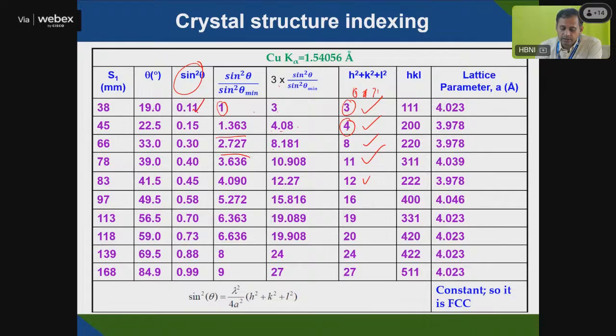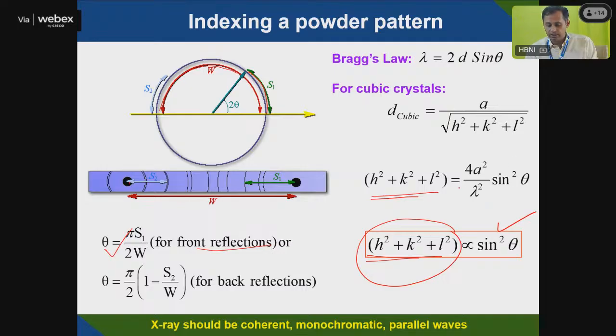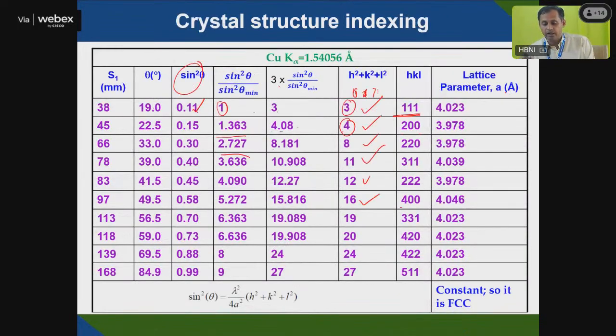Now you can see the 3, 4, 8, and how you can express the HKL value. 1, 1, 1 will be 3. 2, 2, 0 will give you 8 for h square plus k square plus l square, and 4, 0, 0 will give 16. After getting this HKL plane, by putting this equation you can get the d spacing, and then you can get the lattice parameter. The lattice parameter is coming 4.0, 3.9, so all are almost constant. That means h, k, l are all unmixed here, so you will get an FCC structure. You can identify easily what my crystal structure is. Indexing is possible by using these simple techniques.